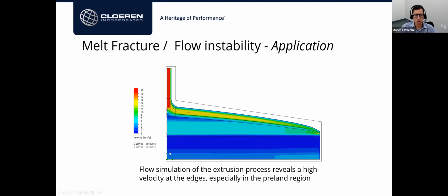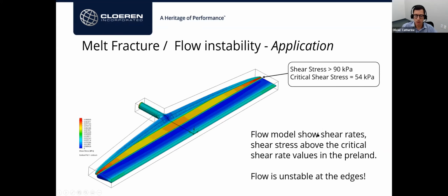So I wouldn't expect the shear stresses or the shear rates to be high in the lip land region. So I ran some flow simulation with the material flow behavior I just determined. And for some reason, this die was trying to push more material at the edges. And you can see that the computed velocity was quite high in the pre-land region there, near the edges. When I looked at a map of shear stress calculated from a flow simulation, I found that the shear stress was higher than the critical value in the pre-land region. So not at the die lips, but upstream.